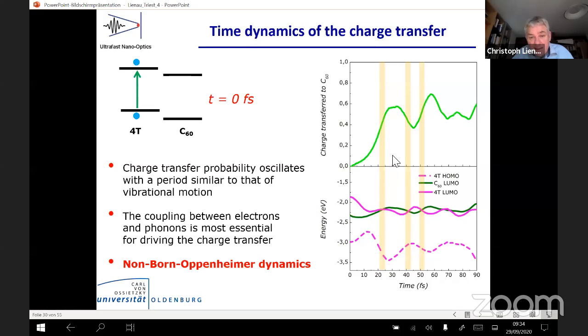There's a relatively easy way to look at this again. Here is plotted in the lower part the time evolution of the energy levels of the HOMO, the highest occupied molecular orbital of the P3HT. That's not so interesting, but also of the lowest unoccupied molecular orbital of the P3HT, and that's the one that is involved in the charge transfer, this one here. Okay, and you see it oscillates like this.